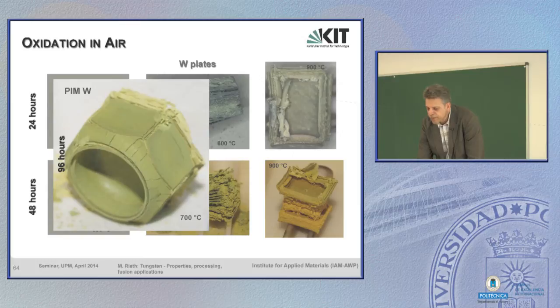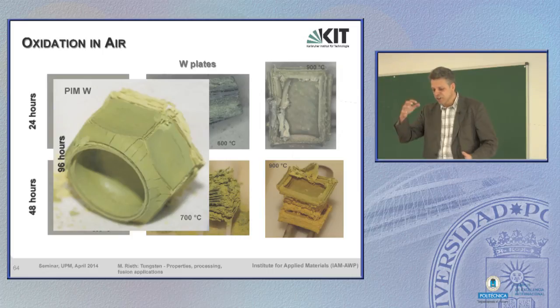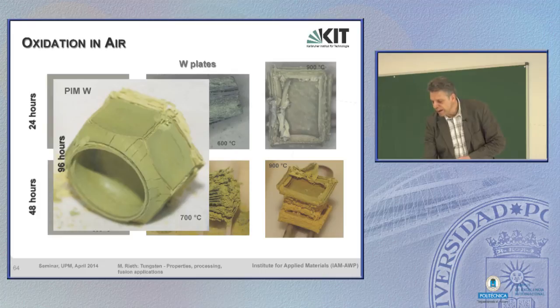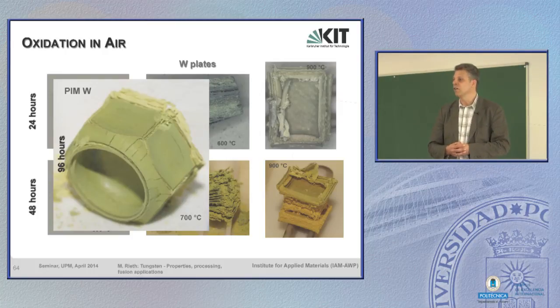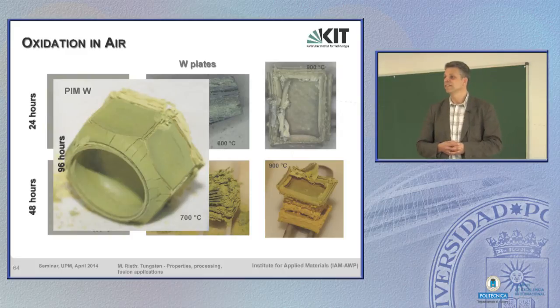It behaves somewhat like a croissant. If you put it in the furnace, they really bake up, they split into multi-layers, and they really lose their form at higher temperatures. If you see here, this has nothing to do with the blade anymore. So oxidation is a killing factor for tungsten application, as you can see.